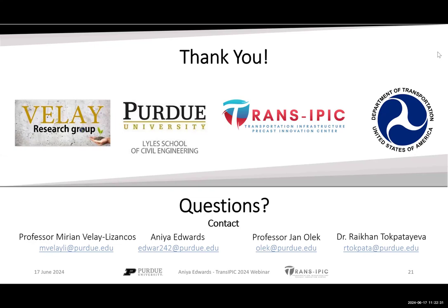We will test it, and we will do corrosion testing to see that indeed, because what is carbonated is not what provides concrete with high pH, most likely we are not getting this reduction of corrosion resistance, because we are not reducing pH, and therefore we will not be reducing, at least not to the same extent, the threshold of chloride to initiate corrosion. That's one point, but we will test it for sure and see the results. So that's one of the things that we really want to do. And in terms of scale up, do you want to respond, Aniya, or do you want me to do that?